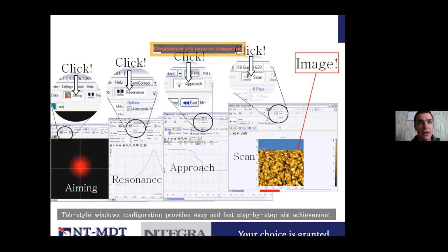In contact mode, we just use the static deflection of the cantilever. In semi-contact mode, we drive the cantilever at its resonance frequency, and then we keep the magnitude of oscillation constant at some level for the feedback loop operation. So if we need to operate in semi-contact, we just click search for the resonance frequency, and the software automatically finds this resonance frequency. Then we switch to the approach window and click the approach or landing button, and the software automatically approaches the tip to our sample.